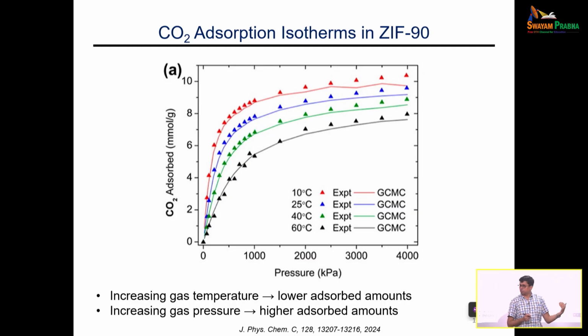Adsorption, like I said to start with, is expected to be an exothermic process. If you have higher temperatures, adsorption is going to be very severely impacted. If you look at the first, this is 10 degrees, this is cold for a process. You can do it in the lab, but replicating 10 degrees in an environment, you need cooling to get there, versus 60 degrees, which is probably the temperature for most flue gases, even after a certain length of the stack. You see the difference in capacity, that is quite a lot. So temperature has a very big impact.